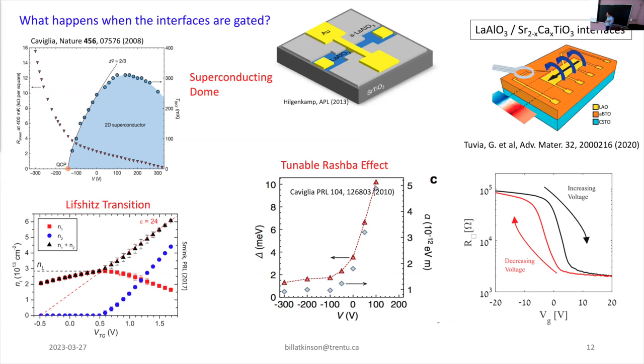And then recently, in the last few years, there have been a number of papers where people have swapped out the SrTiO3 for something that is ferroelectric. And the data here on the right shows the sheet resistance as a function of gate voltage. And you can see you're getting almost a two order of magnitude change in the sheet resistance, and that there's hysteresis. And the hysteresis is an indication that the ferroelectricity is coexisting with the electron gas. And that's already a little bit of a surprise because the conventional wisdom is that a free electron gas suppresses ferroelectricity.